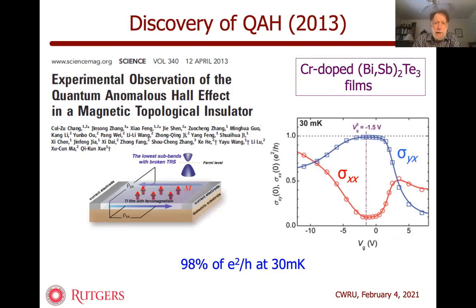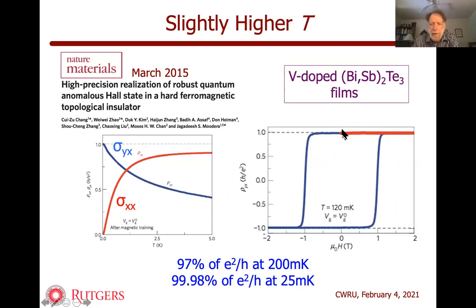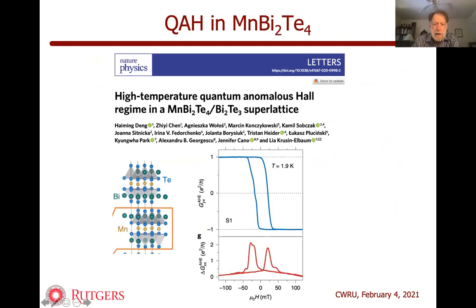This type of system is not intrinsically limited to low temperature — we get up to about 10 Kelvin at the moment, but we don't think there's any fundamental limitation why this could not be observed at 100 Kelvin or maybe even room temperature. There are three types of systems where the quantum anomalous Hall effect has been observed. One is taking three-dimensional topological insulators of the bismuth selenide class and doping them with magnetic dopants to make a magnetic semiconductor. The vertical axis here is the transverse conductivity σ_xy in units of e² over h. This was the first 2013 paper, at 30 millikelvin. This group and others improved this by vanadium doping, and now you're up to 120 millikelvin.